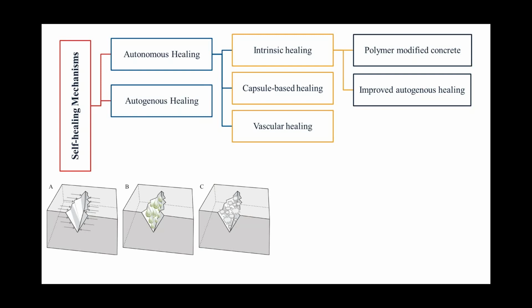And also, in process B, as you can see, providing the water resources for the concrete to help the self-healing. One of the items that recently has been used is the use of super absorbent polymer, SAP. This kind of polymer has a tendency to keep the water inside, and whenever cracks happen, they're going to release that water, and that water